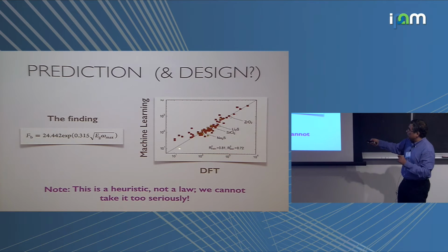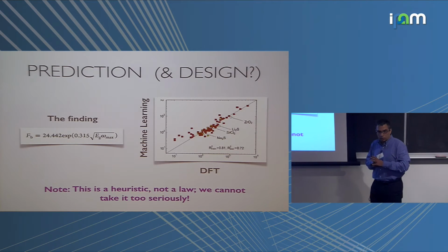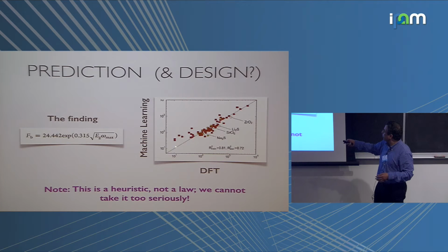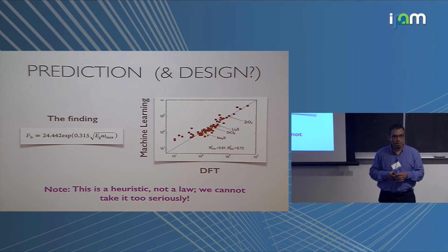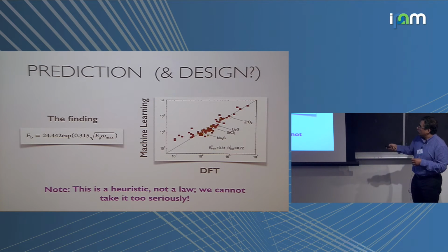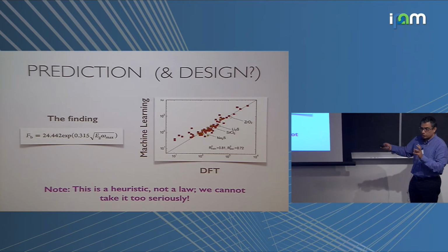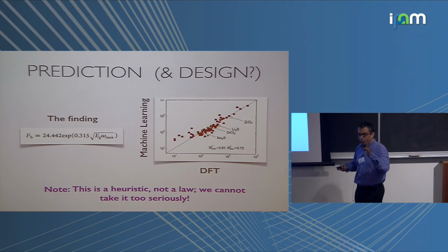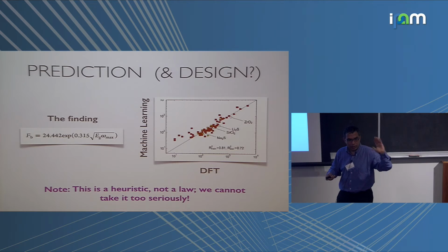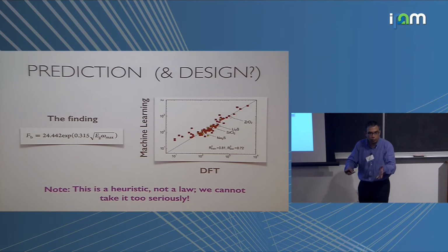And as you can see, the correlation is not super accurate, but it is quite interesting that we can get things somewhat right over 3 orders of magnitude. So now that's exciting. Because we have now established somewhat of a relationship between the intrinsic breakdown field and some easily accessible properties which we can compute with no problem.